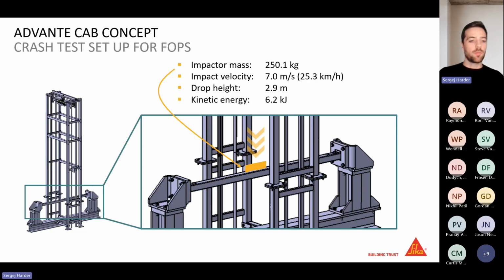So afterwards, we wanted to put our connection to the test. So we set up a crash test. In our case, the FOPS was the more critical load case. So we tested the FOPS and also simulated it. And for the ROPS, we took our validated model later to confirm the reliability of our design. So for the FOPS, we had this crash test with 250 kilograms of impactor mass dropping from a height of around 3 meters.